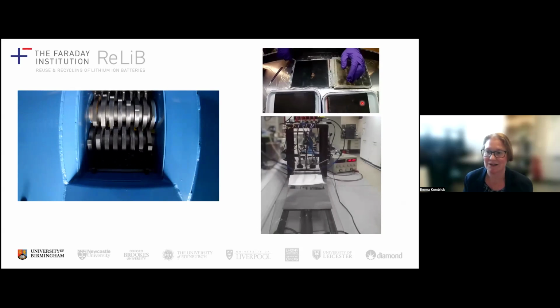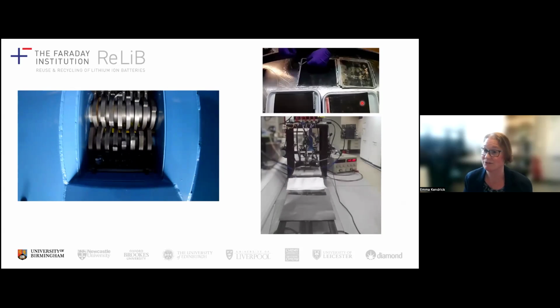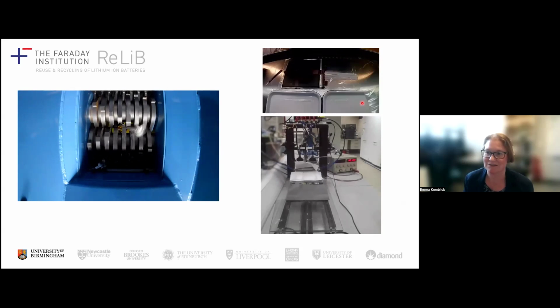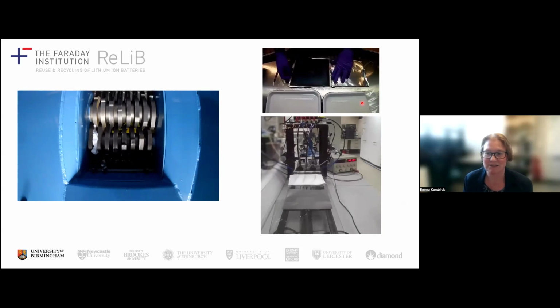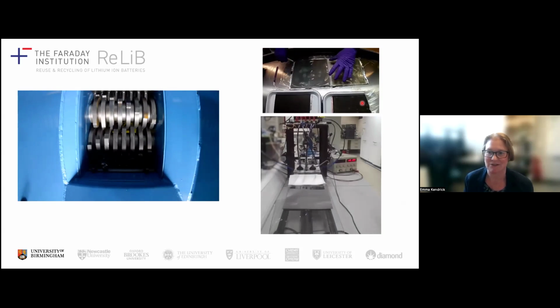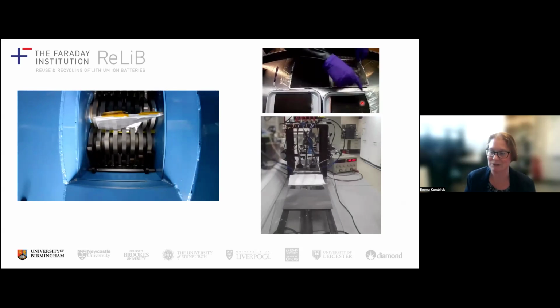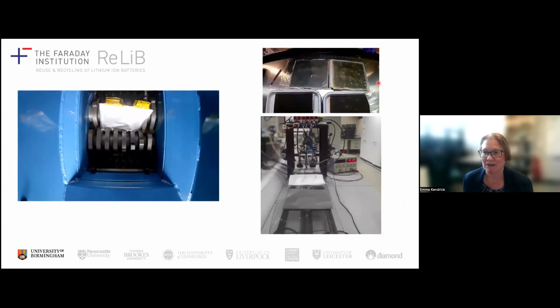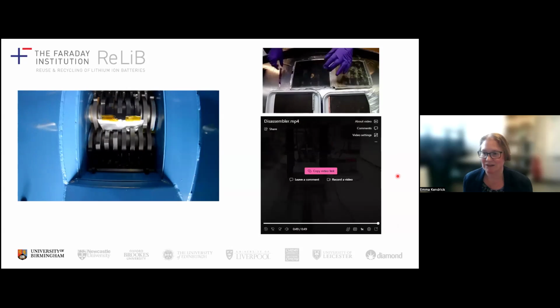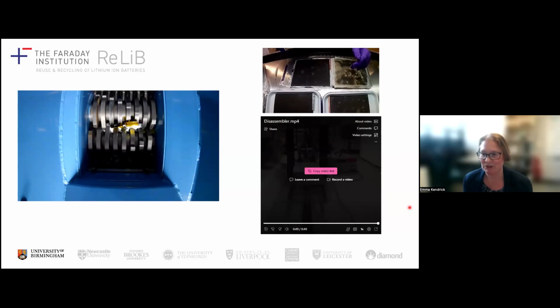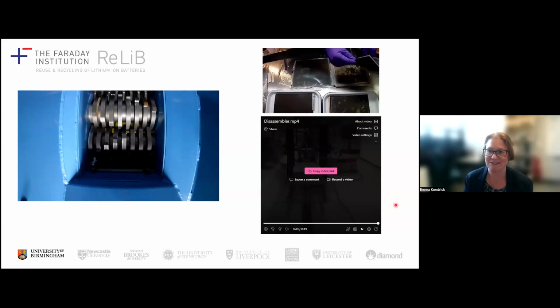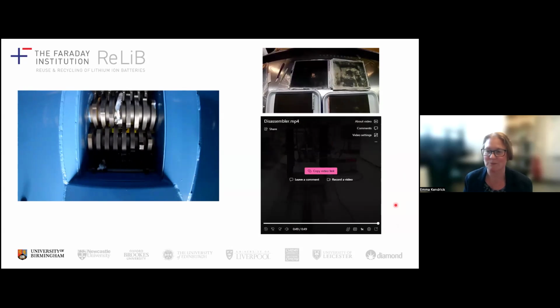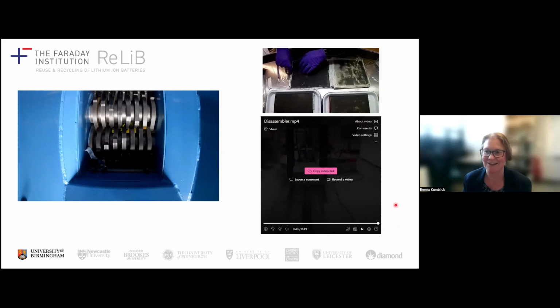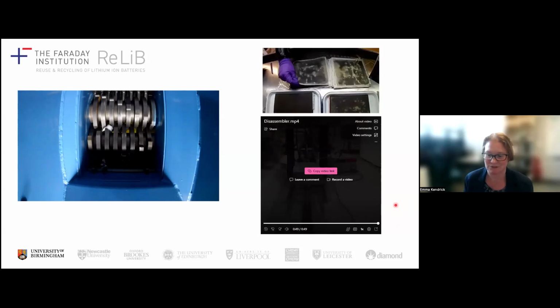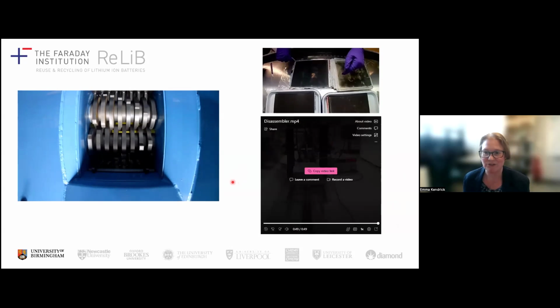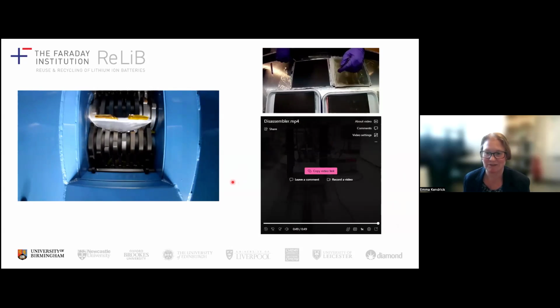The top shows one of our researchers in a lab under a fume hood, I might add, doing some disassembly very carefully of some cells to try and separate out the anodes and cathodes so that we get less impurities in our streams for then reprocessing. Whilst we're also looking at trying to automate this, and in the video below you saw some automation of trying to identify the cathode, the anode, and the separating material so that we can separate them out again to try and look at creating purer materials waste streams so we can reuse some of these materials with as little processing as possible.